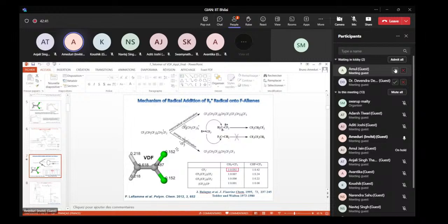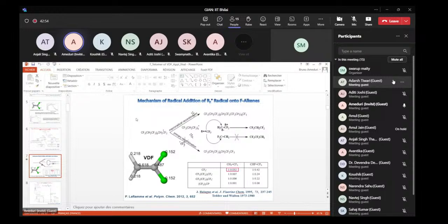But in the case of the use of fluorinated radicals, just like CF3, usually we favor the recombination of macroradical rather than the primary recombination. This means that you have this growing radical reacting onto the primary radical released from the chain transfer agent.